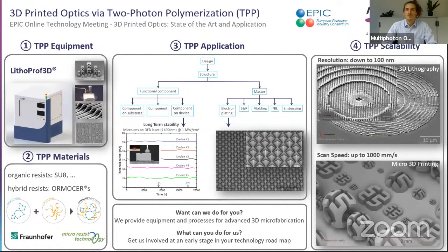For example, you have here a picture of an electroplated replication tool. There we have some pyramidal structures replicated in a very huge area. Going back to the functional components, the material class of ORMOCER has a very high optical resistivity, making them ideal for functional components. This test is a micro lens fabricated on a DFB laser, and the optical power was at a megawatt per square centimeter. And since now they are running for over 2 years and looks quite good, but they will run on and on. And the scalability of this technique is the resolution down to 100 nanometer.